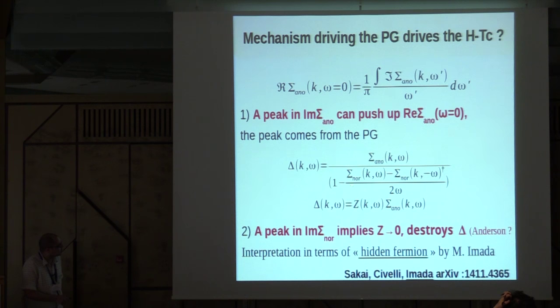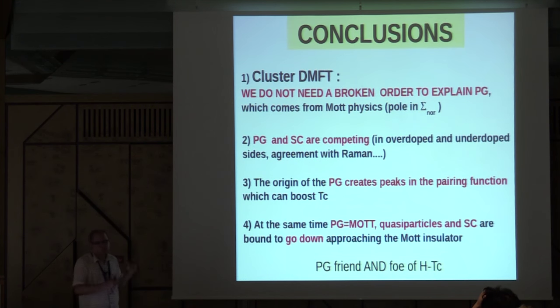Of course, once one looks at the gap function, which is the one you look at in the spectral functions, in the spectra you take in experiments, there is a Z that has to multiply this anomalous self-energy, which depends on the normal part of the self-energy, which has the peak. So if this goes to 0, close to the Mott transition, this would destroy the gap. This comes back a bit to the idea of Anderson, actually. So as a matter of fact, this is the end of my talk. This poses more questions than it gives answers. The structure of the pseudogap looks different, but in some way seems to help superconductivity. And it is not too far from what Anderson was talking about with preformed pairs, if you want. It's not far from that, this fact that the peak is appearing in the self-energy.